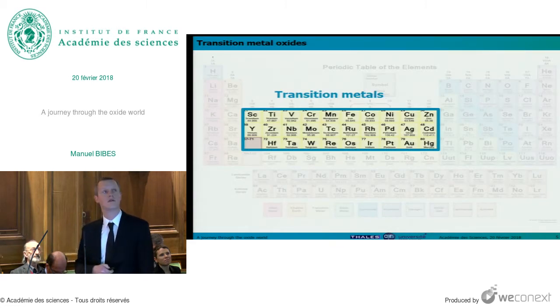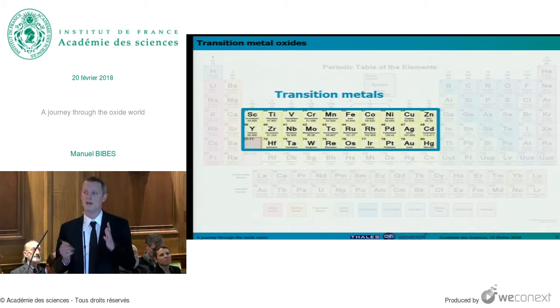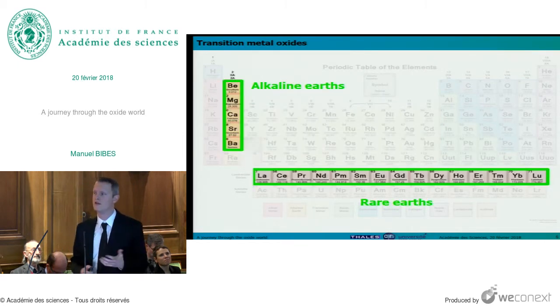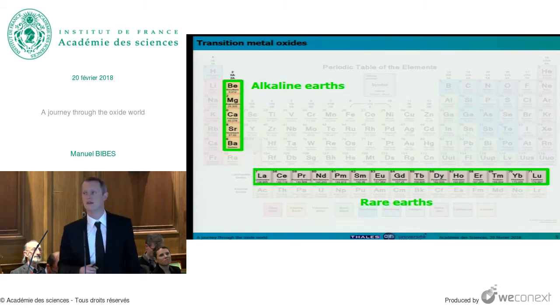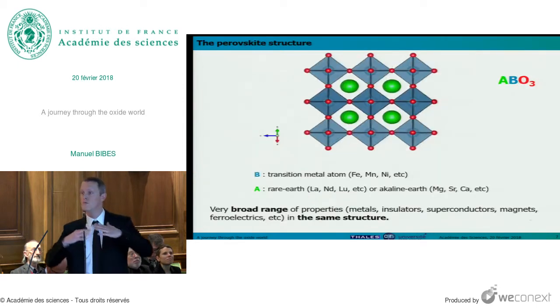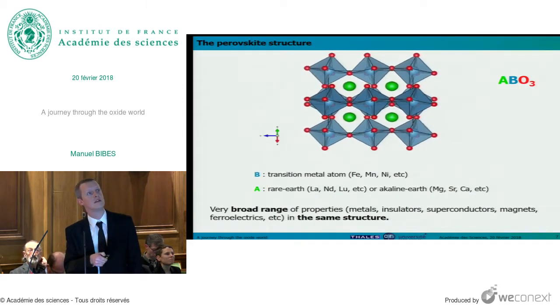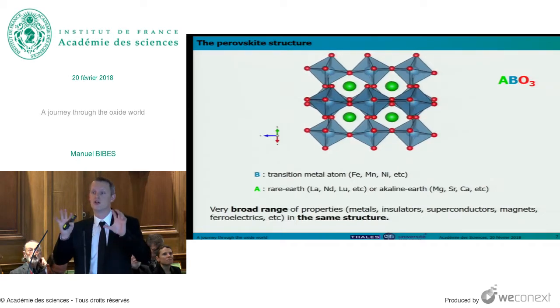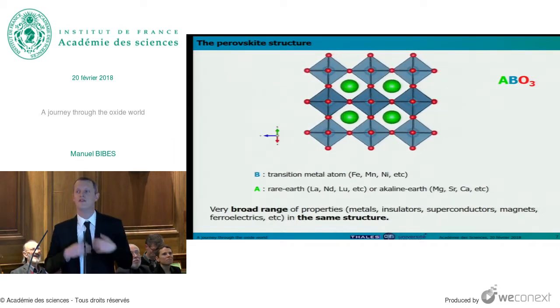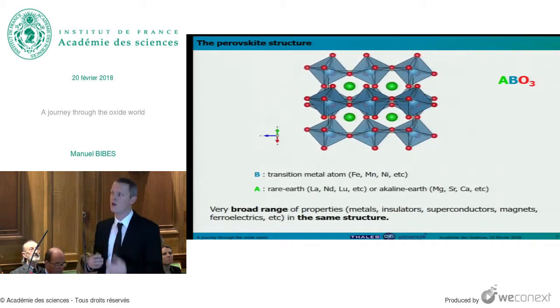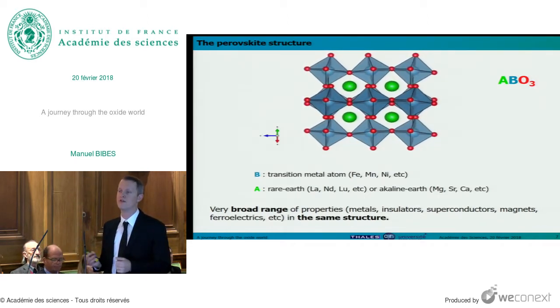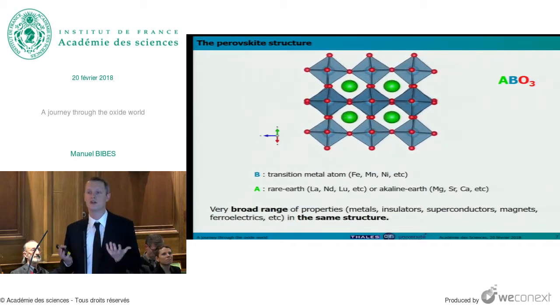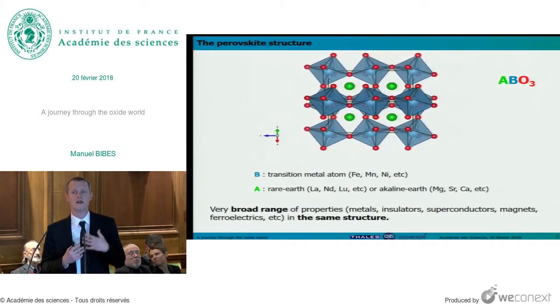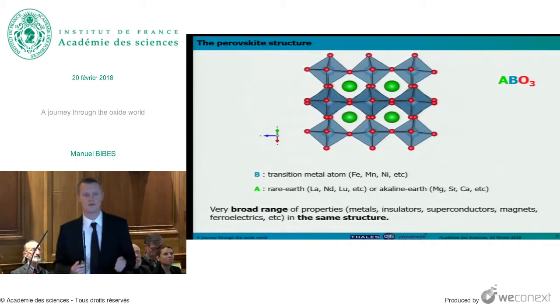elements called alkaline earth. Most of the properties of the perovskites are determined by the atom at the B side, so the titanium, iron, manganese, and the atom at the A side, depending on their size, is going to modify the structure, and you can see that this will provoke some rotation of this octahedra, and this will tune the properties. Because in this perovskite structure it is possible to accommodate so many different elements, they exhibit a very broad range of physical properties.